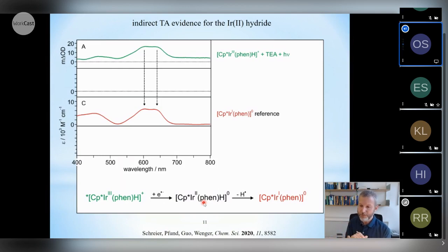There is indeed reductive MLCT quenching, but then here we have an intermediate comprised of iridium-2 hydride where the metal-hydrogen bond is very, very weak. We estimate it's on the order of 50 to 55 kcal per mole. So it's highly reactive and it wants to give away its hydrogen atom, and you will then end up with this more stable compound. So this is a classical case of A to B to C reaction kinetics where you cannot observe the intermediate B because the reaction from B to C actually is faster than the reaction from A to B.